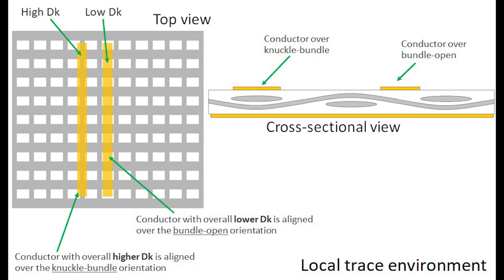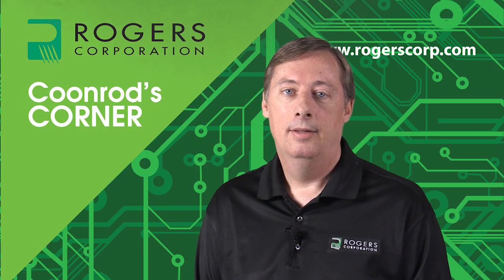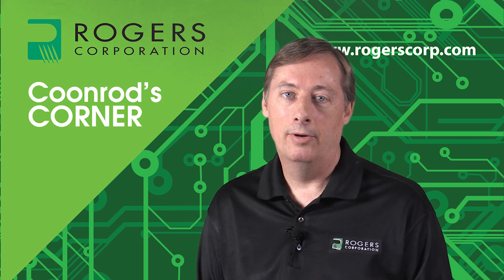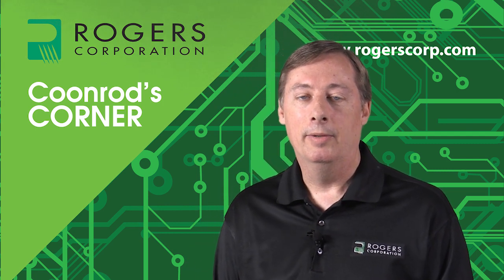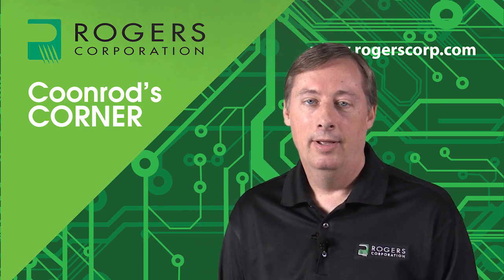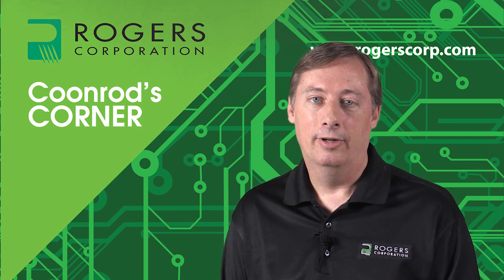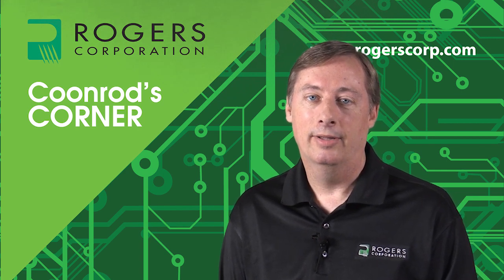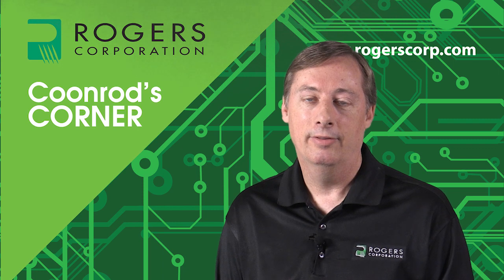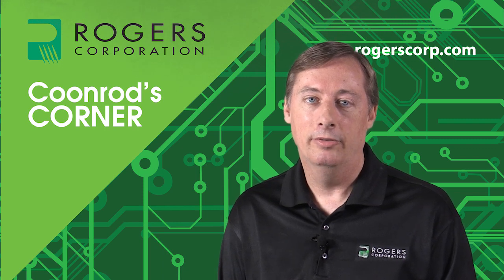To the right of this is shown the same type of configuration, except it's a cross-sectional view. You can see that the conductor over the bundle knuckle area is actually over two layers of glass, and the conductor over the bundle open area is just over one layer of glass. The periodic Dk variation is probably more of a problem at millimeter wave frequencies than the local trace environment. I say that because I've looked at a lot of different circuits in many studies I've done, and it seems to be more of an influence on millimeter wave performance than the local trace environment.